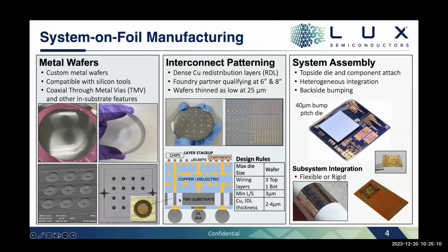This blue and this kind of faded blue or gray is all dielectric, and so any signal that is routed from the top through the through metal via to the bottom is all electrically isolated from the rest of the metal substrate. And then this first layer here on the top and bottom is just a dielectric layer, and then we pattern it and fill metal wherever we want to push signal through the substrate. So there's never an occasion where signals that are supposed to be electrically isolated from the substrate are being connected to the substrate.